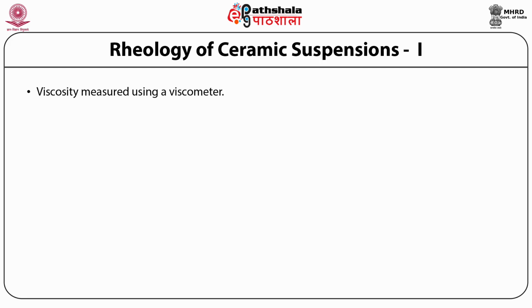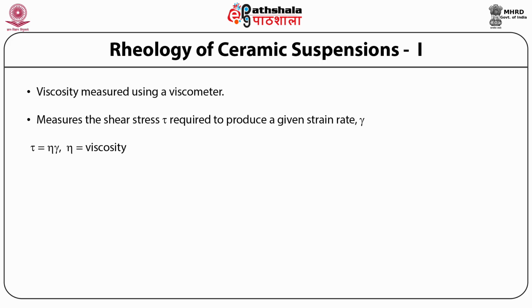The viscosity of a suspension is measured using a viscometer. The shear rate used for measuring the viscosity can be varied. For a given shear rate, a shear stress is applied by the viscometer. The ratio of the shear stress to the strain rate is called the viscosity, or it is given as tau is equal to eta gamma dot, where tau is the shear stress and gamma dot is the strain rate.